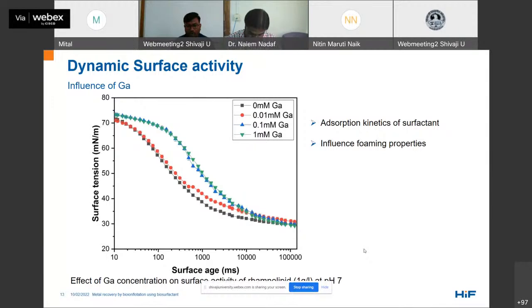Studying dynamic surface tension activity is required because it is used to quantify the adsorption kinetics of surfactant and is considered to have a strong influence on foaming properties. The faster the dynamic surface tension drops, the faster the surfactant molecules or the complexes of surfactant and metal adsorb at the air-water interface, which increases the foamability as well as foam stability of the frother.